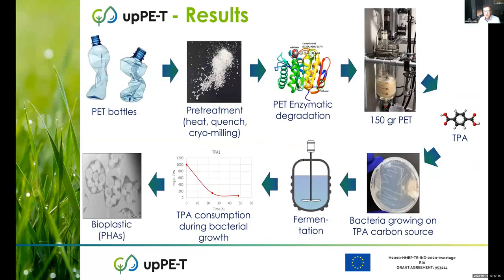So a brief overview of some results. Typically, we take PET bottles, we grind them up, and we make sure that we have small pieces because that favors a fast enzymatic conversion. Then we add the enzyme, in this case, the PET degrading enzyme. These are known. Many, many groups in the world are looking for PET degrading enzymes, and very successfully so. In our labs, we've scaled this in a decent size reactor of 10 liters, where we can do 150 grams, 200 grams of PET conversion all the way down to terephthalic acid.